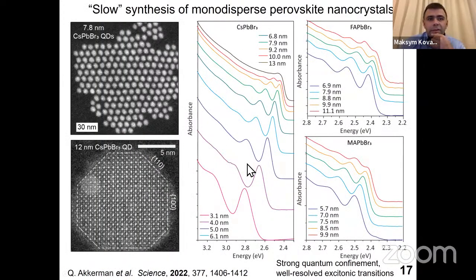Now, one of the reasons why this synthesis is beneficial is that you can also expand it to hybrid perovskites, which have been traditionally very difficult to produce because they are much more fragile. And now we can produce formamidinium lead bromide or methylammonium lead bromide with the same degree of size control, down to very small sizes. So with this new synthesis, you can isolate extremely small nanocrystals, down to 3 nanometers, in a large quantity and with the retention of stability throughout the purification. But what's also very special is that your dots are no longer cubic, they can be of spherical shape.